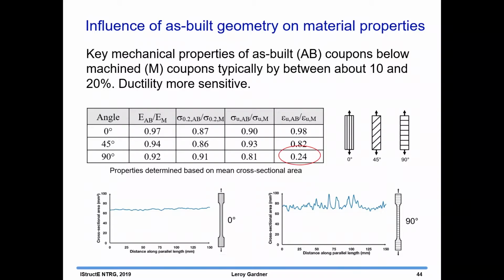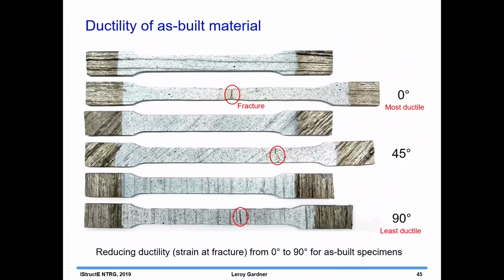But ductility was more severely affected, particularly for the coupons that were tested at 90 degrees to the printing direction, because you're pulling across the largest undulations and across the weak points between the successive layers. And you could see that clearly in the failed specimens.